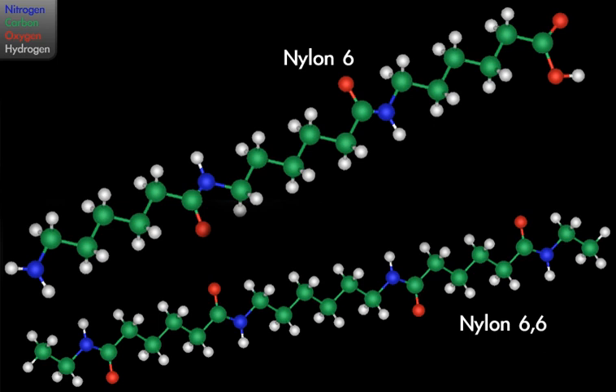Topic: Blends. Most nylon polymers are miscible with each other, allowing a range of blends to be made. The two polymers can react with one another by transamidation to form random copolymers. According to their crystallinity, polyamides can be semi-crystalline: high crystallinity, PA46 and PA66; low crystallinity, PAMXD6 made from m-xylylenediamine and adipic acid; or amorphous, PA6I made from hexamethylenediamine and isophthalic acid. According to this classification, PA66, for example, is an aliphatic semi-crystalline homopolyamide.